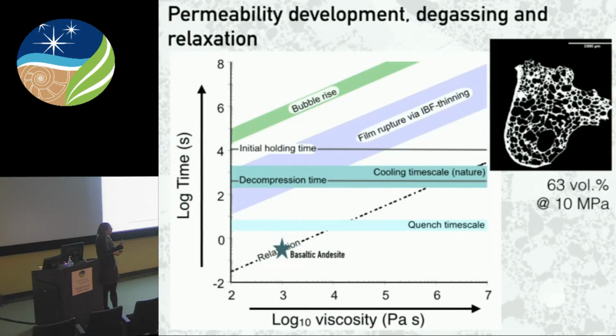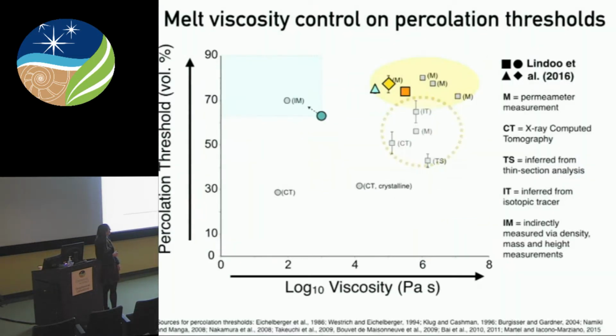And then the relaxation of the bubbles could reseal some of these permeable pathways that initially we think were in the magma, along with the bubble shrinkage due to internal pressure loss. So using our highest vesicularity measured as a lower bounds for the percolation threshold, we predict that the basaltic andesite melts have a percolation threshold higher than 63 volume percent. And this agrees with another study.